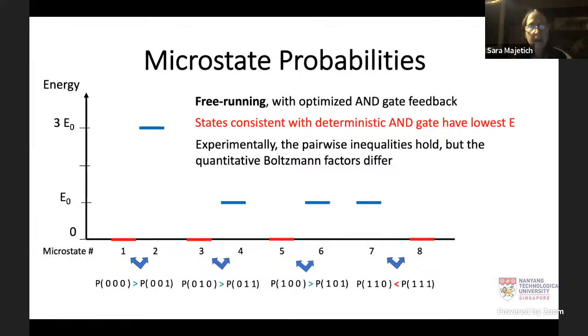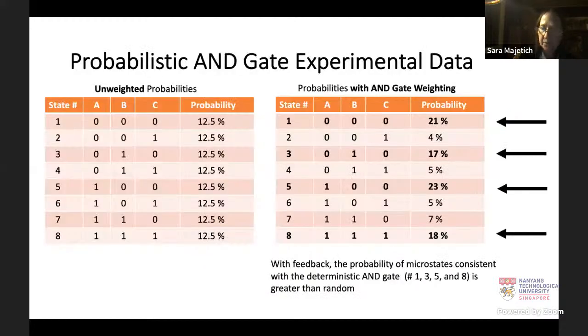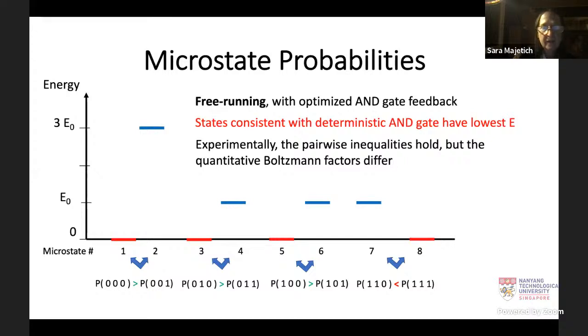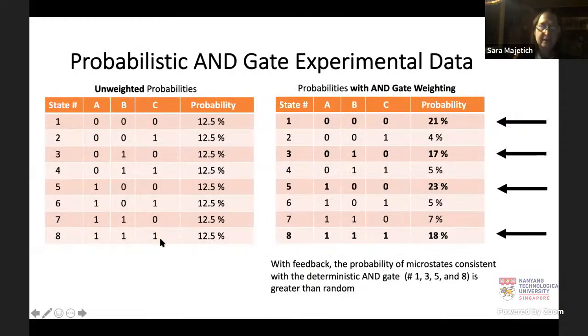So really, one way that we have found useful to look at this is to think about the energies. So with the different feedback that you give, how do you choose it such that you have different energies for these states, and that you're favoring the 4 states that you want and heavily disfavoring the ones that you don't. So if you look at them pairwise, you can see of the 8 microstates that there are pairs that differ in the output C, and one of them is consistent with the AND gate and one isn't. And so we're able to design circuits that favor those states.